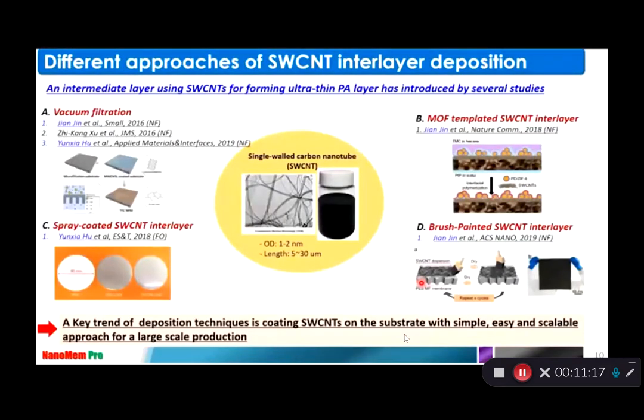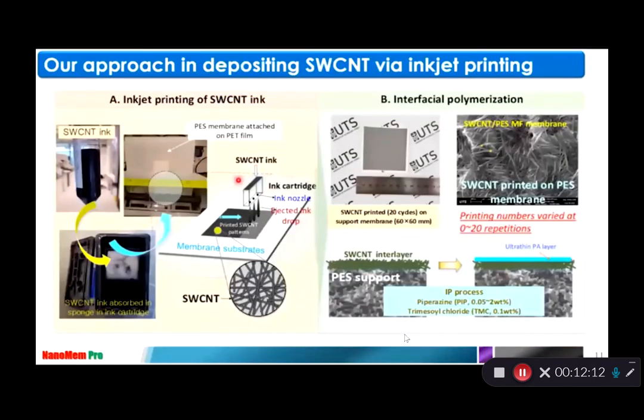and then see how we can better separate the organic solvent. So if you look at the different nanomaterials, we have selected SWCNT interlayer deposition. In previous studies, they tried to utilize a vacuum filtration system, a spray-coated SWCNT interlayer, and a MOF-templated SWCNT interlayer, or brush, just simply brush-painted SWCNT interlayer. So there are many different methods to coat your CNT as an interlayer, and the key trend of the deposition technique is coating SWCNT on the substrate with a simple, easy, scalable approach for large-scale production. That's the reason why we try to combine SWCNT with the inkjet printer.